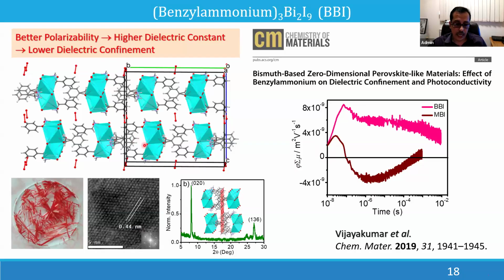Okay, and in addition to that, we have found one aspect. We studied the film state property and found that the film growth is controlled by the organic component. Normally, in a perovskite system, the film growth is controlled by the inorganic part, that is the octahedral thing. But here it is controlled by the organic part, and that is a novel observation.